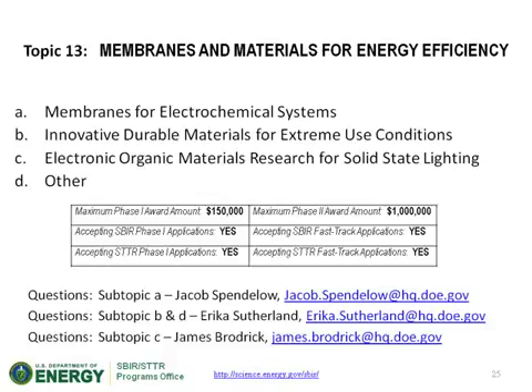I'm going to speak on behalf of topic 13B, which is innovative durable materials for extreme use conditions, and also 13D, which is the other category. The technology manager responsible for that is Erica Sutherland, but I'm going to speak on her behalf for these subjects. Right now we've identified a gap in the deployment of hydrogen fueling stations, where we need to look at polymer materials in extreme environmental conditions. These conditions involve hydrogen, but also high pressures, up to 100 megapascals or close to 1,000 bar, and a variable temperature range from around minus 50 degrees C up to 200 degrees C. With these technologies, we're looking to make them lighter weight and cost effective.